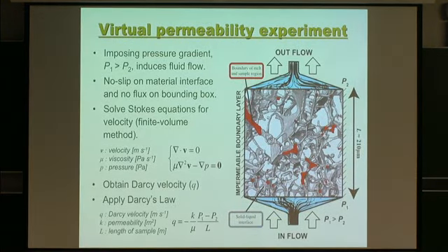So with that, we can conduct this virtual permeability experiment. Now this is a 3D subvolume of that sample, right? And we add a thin layer of boundary before applying the pressure gradient. The reason you do that is that if you don't, then immediately the flow only goes through one or two of the really large channels, all right?